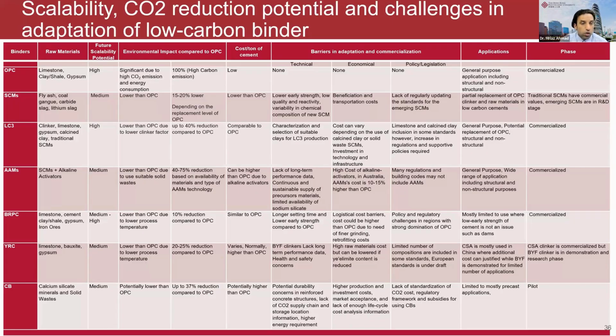So therefore, when we're talking about the decarbonization of cement, it requires a very multi-pronged and prolonged approach. We have to leverage different technologies in different contexts and different regions. A few different kinds of binders can be very effective in different environments, such as geopolymers or magnesium phosphate cements. They're extremely good against chemical attacks, or for nuclear waste stabilization. So it depends. I think we can prioritize which binder is suitable for which application, and we can effectively reduce the carbon emission from cement.